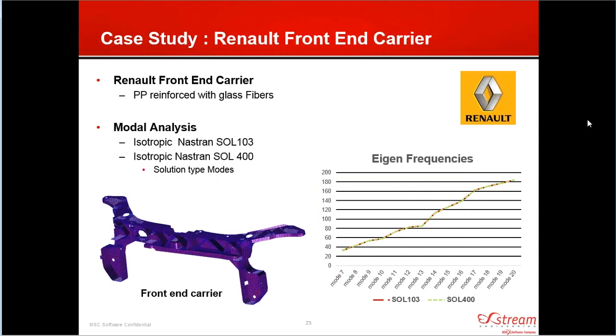So here is a case study to demonstrate how that might work, or what kind of accuracy you can expect out of Solution 400 for our Solution 100 users out there. This is a short case study we did with a Renault front-end carrier, which is polypropylene reinforced with glass fibers. In the first step, we wanted to compare Solution 103 to Solution 400. So really looking at a modal analysis just to make sure that as we move from one solution type to the next, we can still expect the same level of accuracy and the same type of results we got with our 100 solution that's really been our legacy solution.